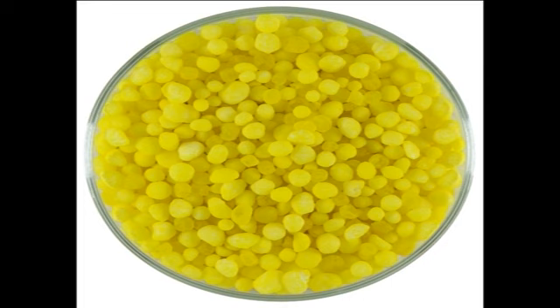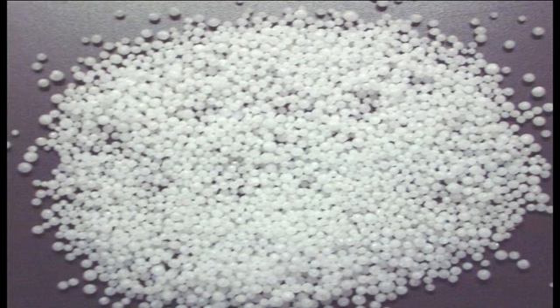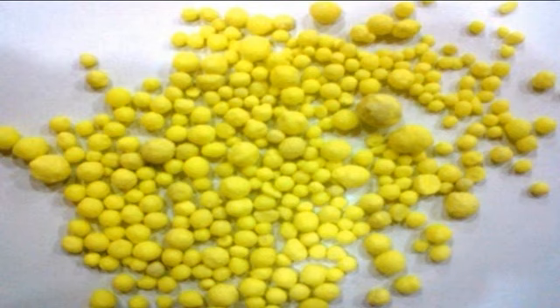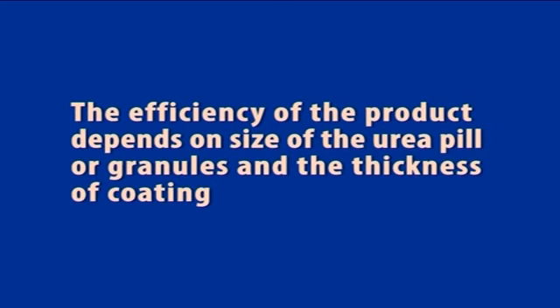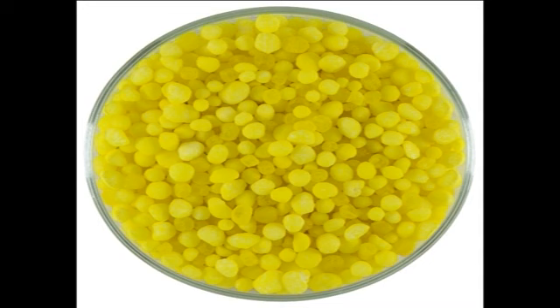One of the first commercialized and extensively studied slow release fertilizers is sulfur coated urea. This is also abbreviated as SCU. Urea granules uniformly coated with sulfur, followed by a wax coating to seal any pores or cracks of the first coating, are found to have slow release property. The efficiency of the product depends on the size of the urea pill or granules and the thickness of coating. The release from sulfur coated urea has been reported to take place by one or more of the following mechanisms.